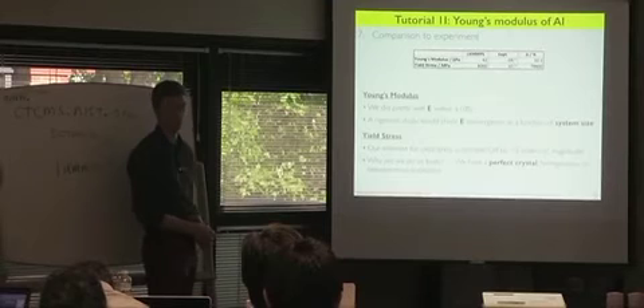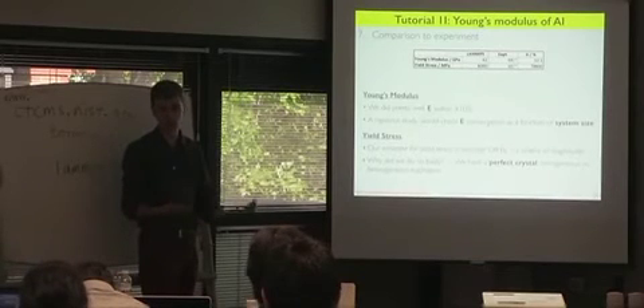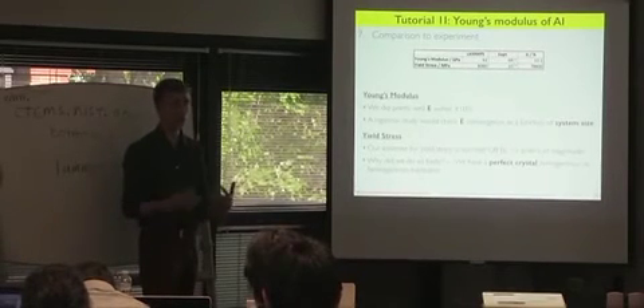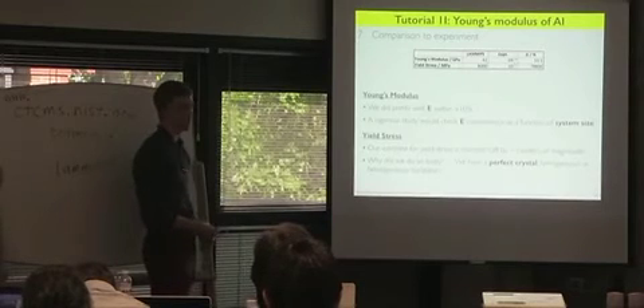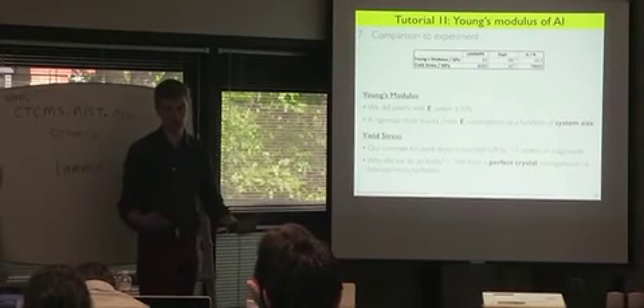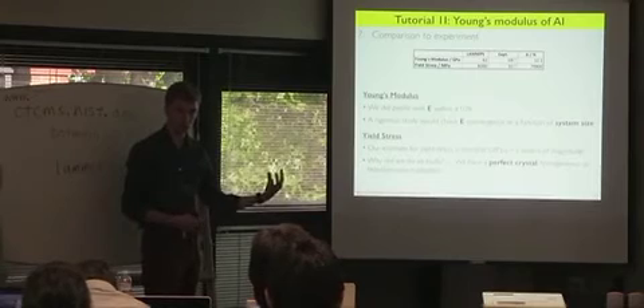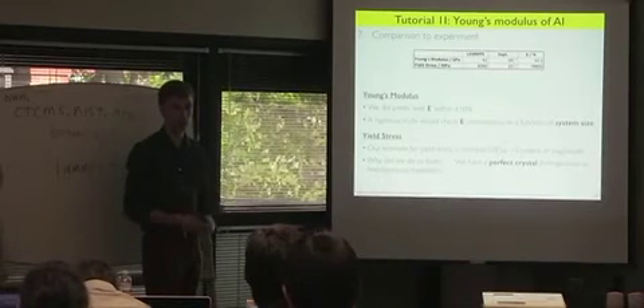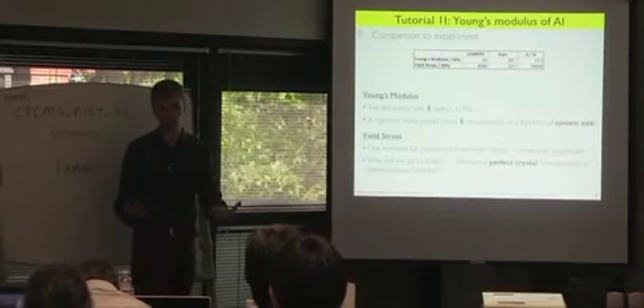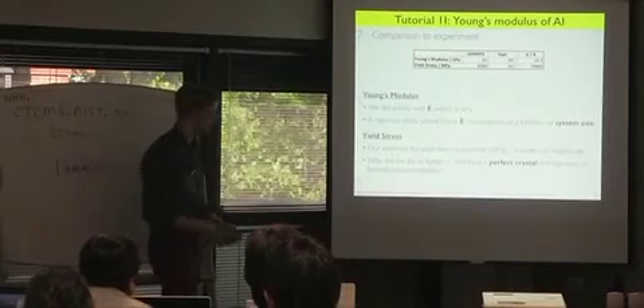Why? We did it in a perfect crystal. So this is the yield stress for homogeneous dislocation nucleation. Really, in practice, things nucleate heterogeneously due to the presence of defects, dislocations, etc. So if you wanted a closer estimate to experiment, you would have to build your crystal with some defects built into it and do exactly this simulation.